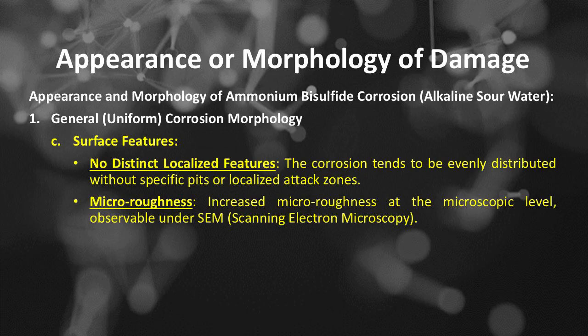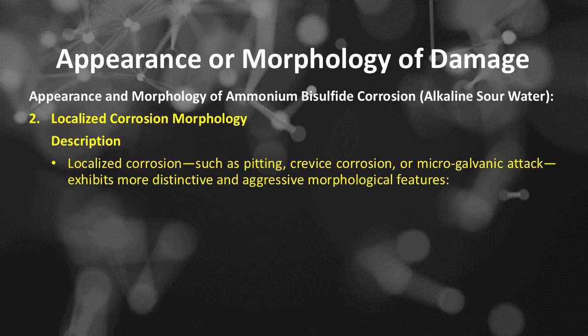Increased micro-roughness at the microscopic level, observable under SEM, scanning electron microscopy. Appearance and morphology of ammonium bisulfide corrosion or alkaline sour water. Number 2 is localized corrosion morphology. Description: localized corrosion such as pitting, crevice corrosion, or microgalvanic attack exhibits more distinctive and aggressive morphological features, including: